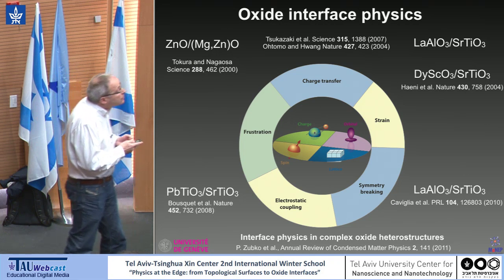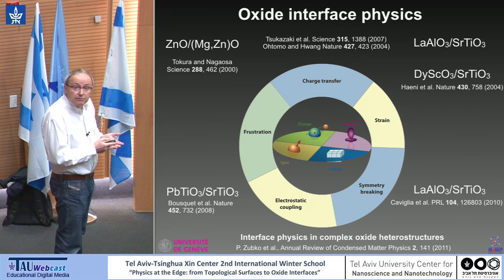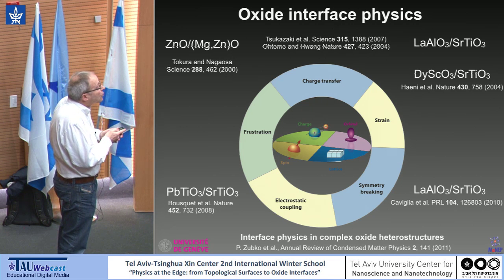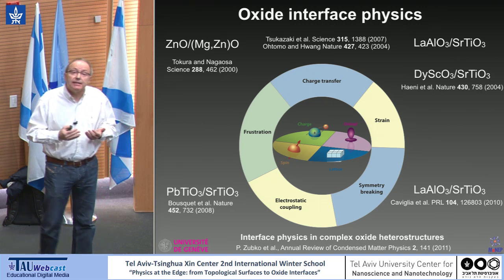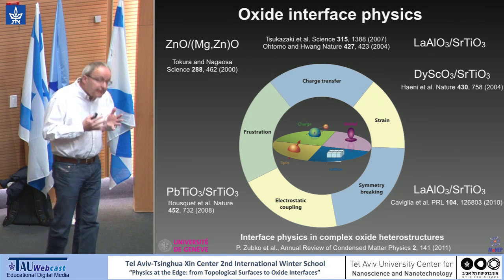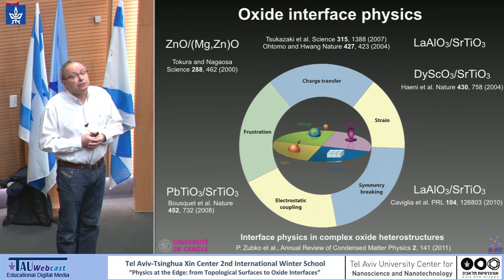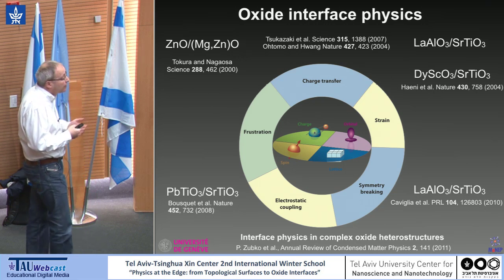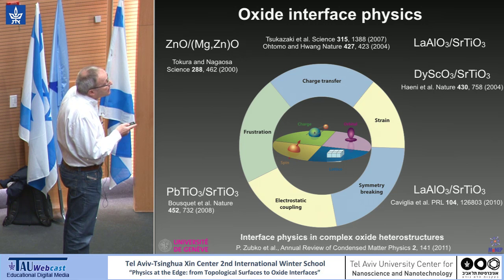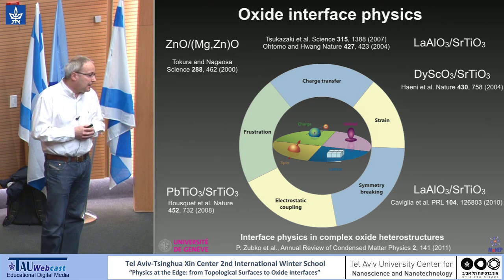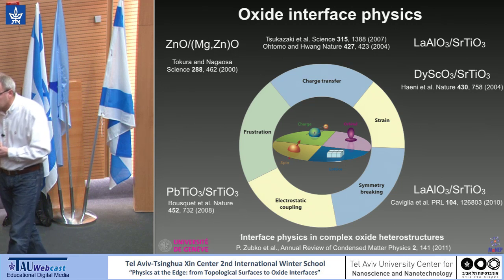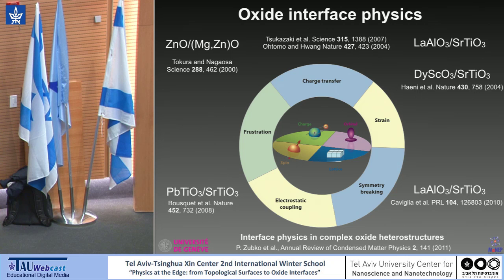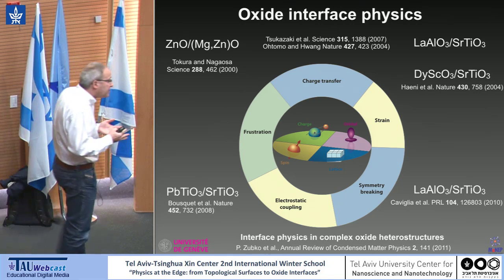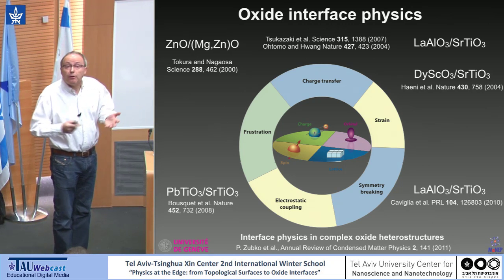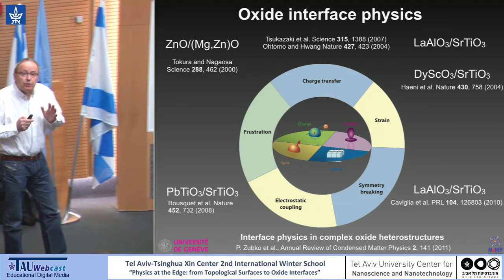new effects. And if you think about the fundamental symmetry breaking which takes place at an interface, maybe strain gradients, charge transfer, frustration, or eventually electrostatic coupling, you realize that at interfaces we may obtain properties which are different from the materials involved in this interface. And the idea is that in oxides, where you have many degrees of freedom, charge, spin, orbital, lattice, this interface will eventually lead to new functionality. So this is a dream of this field of research, which is to use oxide interfaces and ideally find new properties, new functionalities.